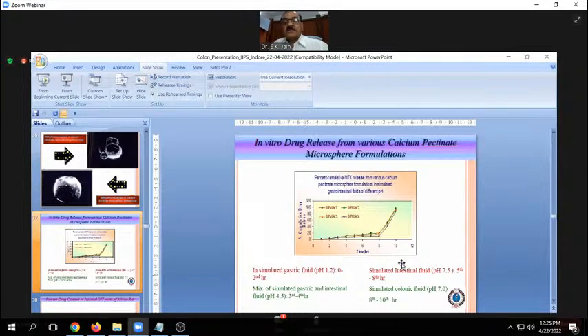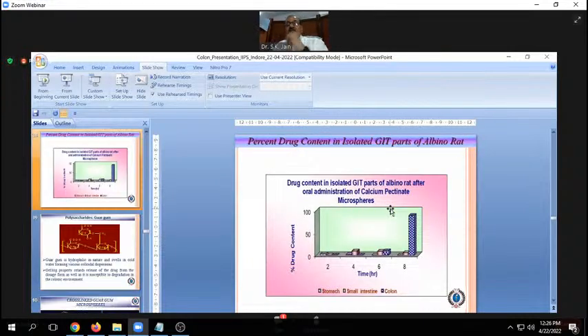These in vitro drug release studies were performed in different simulated GIT fluids, say simulated gastric fluid, pH 1.2, for 2 hours. Then a mixture of simulated gastric and intestinal fluid, pH 4.5, for 3 to 4 hours. Then pH 7.5 for 5 to 8 hours, and simulated colonic fluid having pH 7 for 8 to 10 hours. We find that after 8 hours, a sufficient amount of drug starts releasing, right? And then we also performed in vivo studies. At different time intervals, we sacrificed the animal, isolated the GIT and its different parts, and checked the drug content in the different parts of the GIT. After 8 hours, we find a large amount of drug present in the colon.